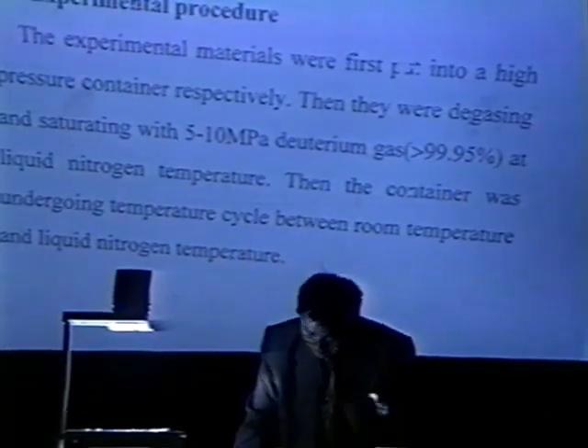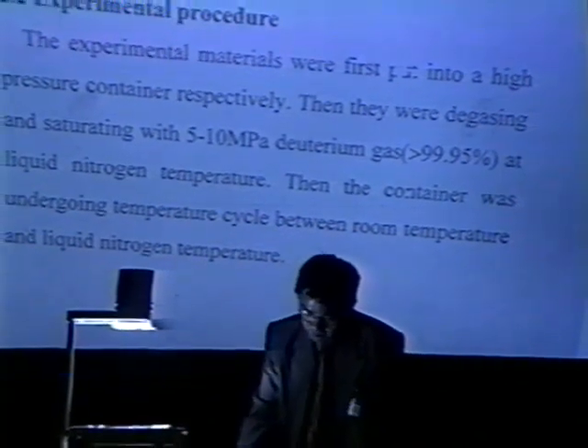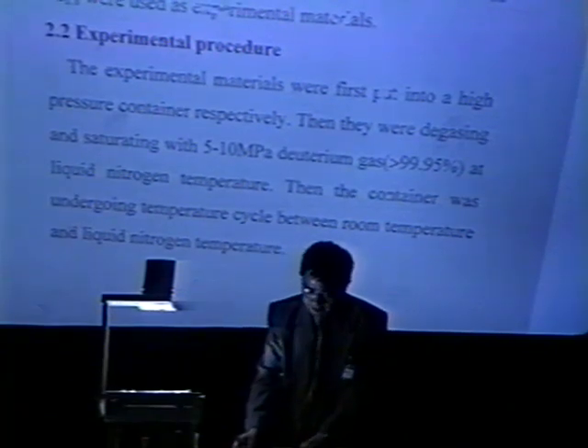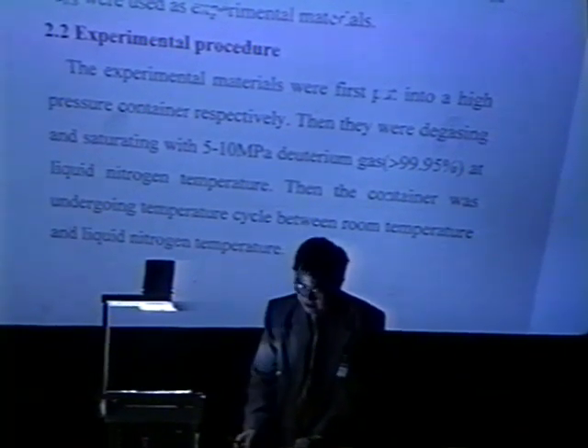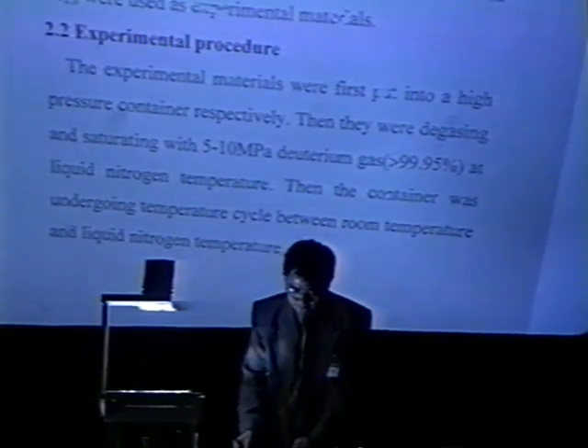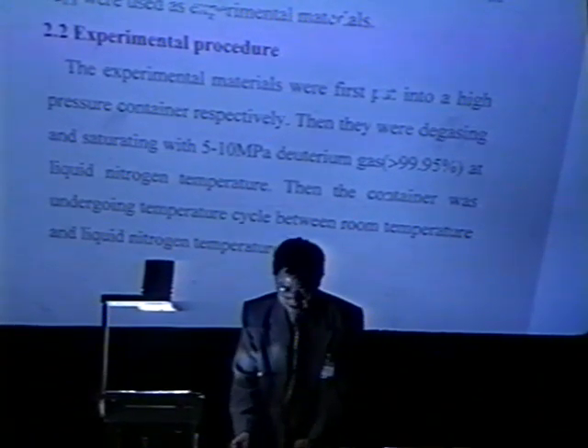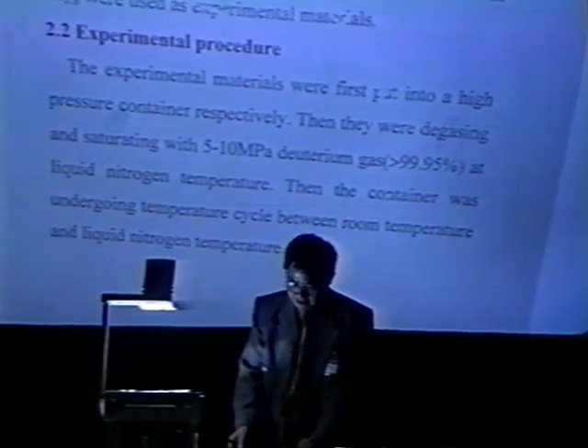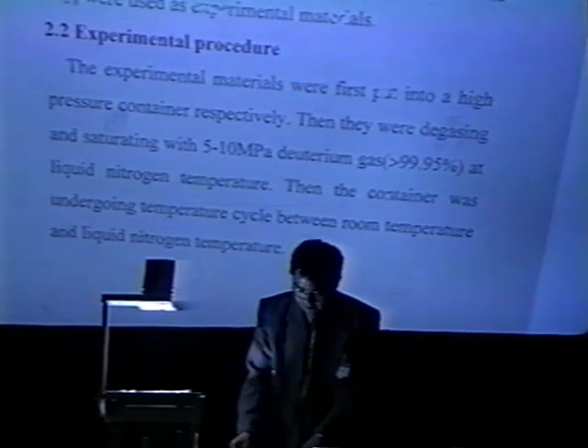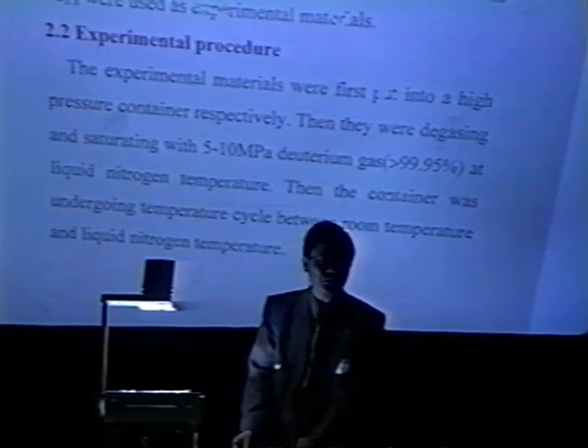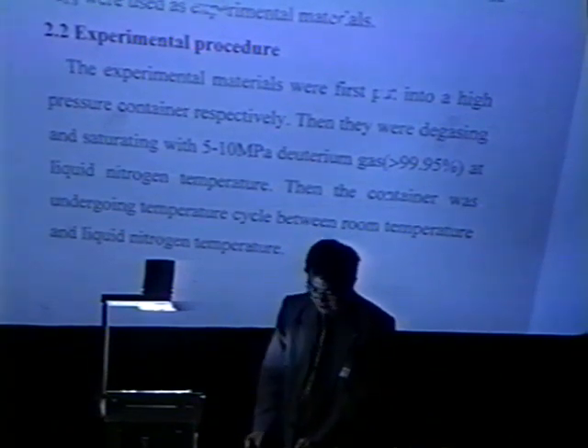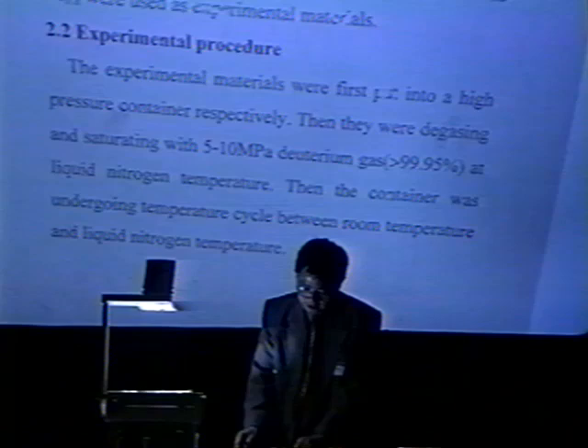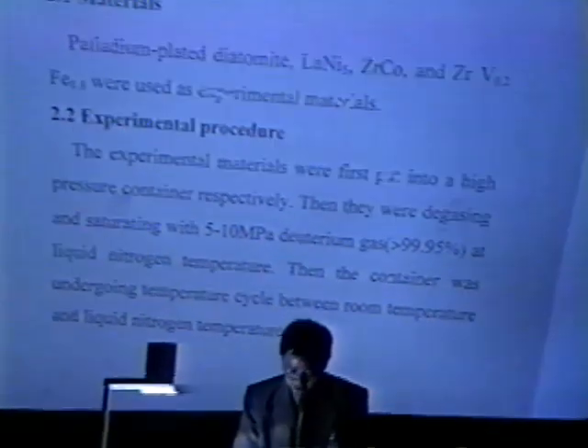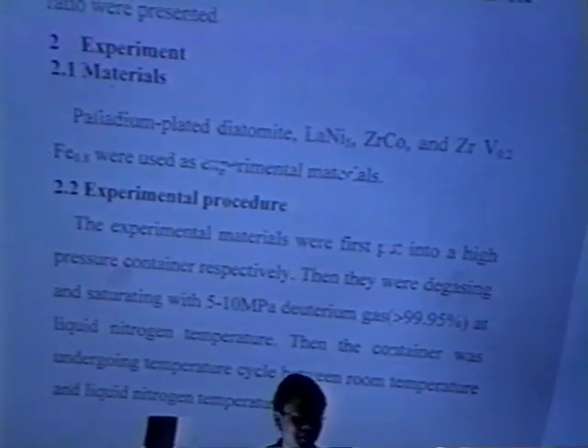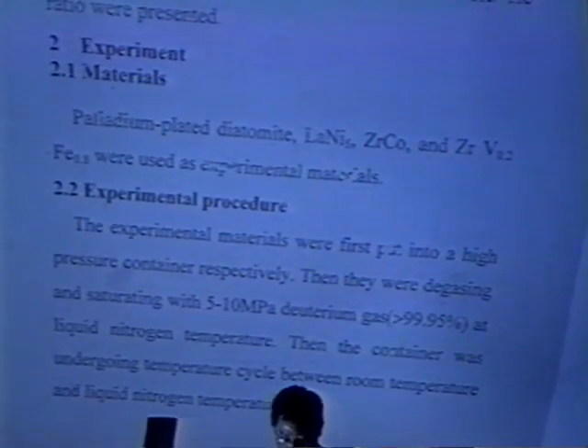Experiment procedure. These experimental materials were first put into a high-pressure container respectively. Then they were degassed and saturated with 5 to 10 MPa deuterium gas at liquid nitrogen temperature. Then the container underwent temperature cycling between room temperature and nitrogen temperature. Then the deuterium gas was released from the container to detect the reaction reactant.